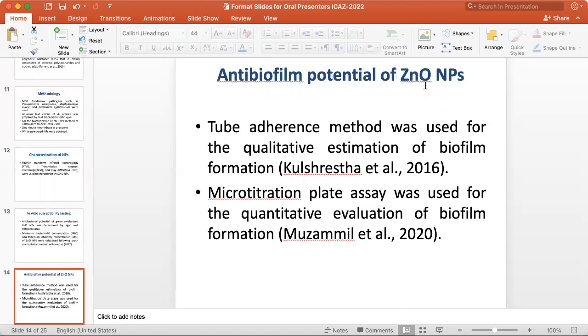For antibiofilm potential testing, two methods were used: one qualitative and the other quantitative. In the qualitative assay, the tube adherence method was used, in which ring formation around the walls of the test tube indicated biofilm formation. The presence of zinc oxide nanoparticles reduced the formation of the ring around the wall, or reduced the thickness of the ring that was formed. Whereas the microtiter plate assay is basically a quantitative estimation of biofilm formers or adhered cells.